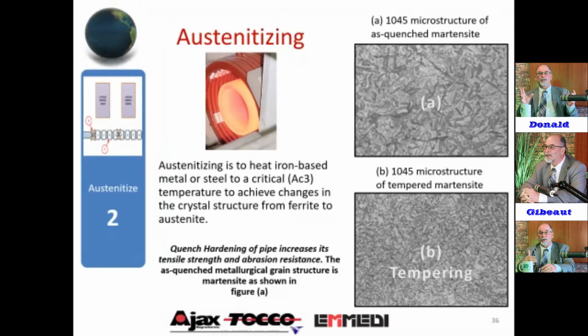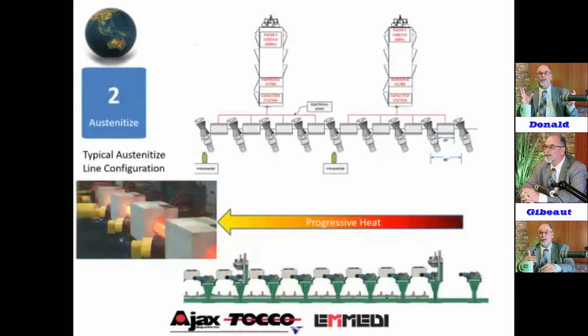The 134 ton an hour line that we're putting down in Houston, starting up in January 2021, does have preheaters for the temper and then a furnace afterwards. So we can work both ways. That particular line goes up to 13 3/8 though, so it's a lot thicker wall, which is another reason they did that.